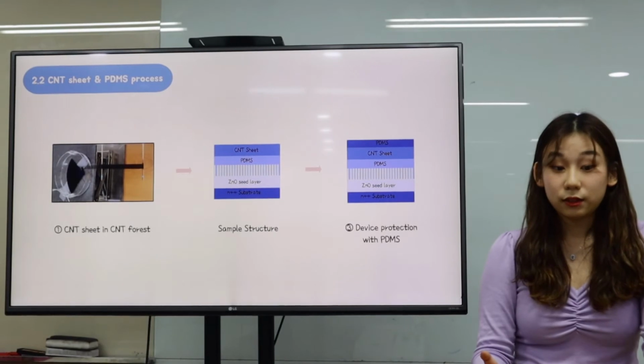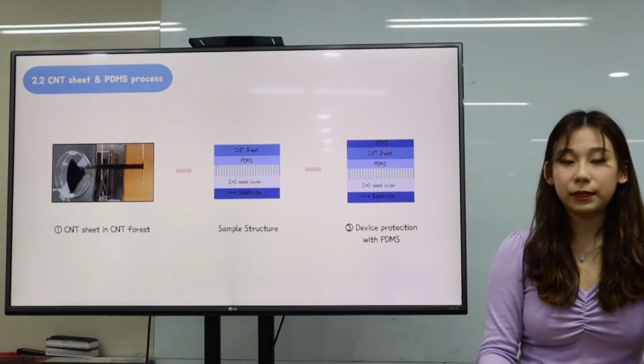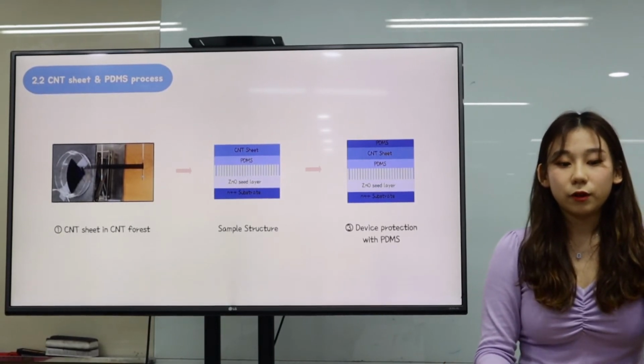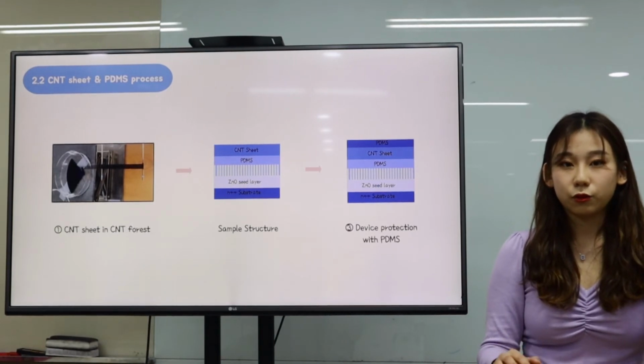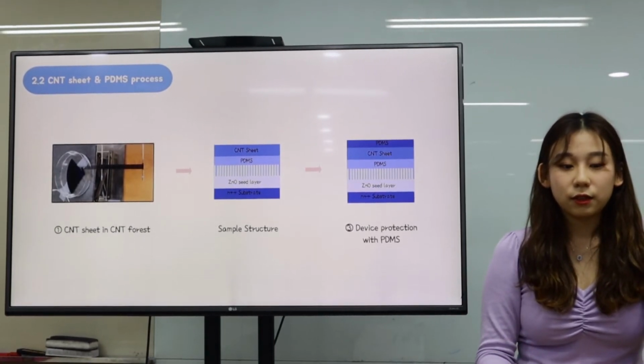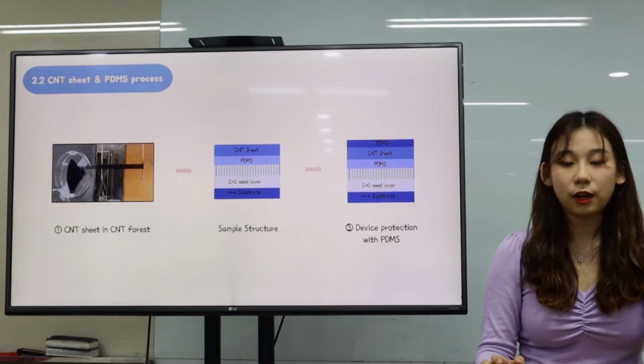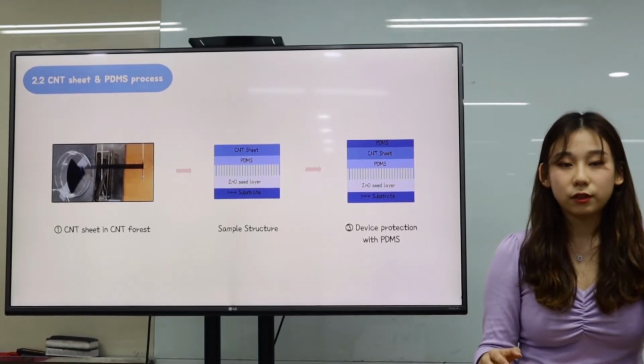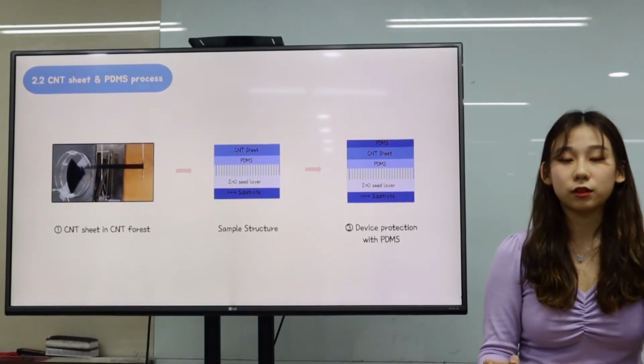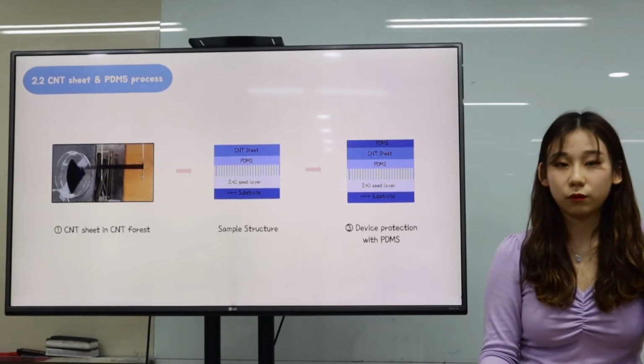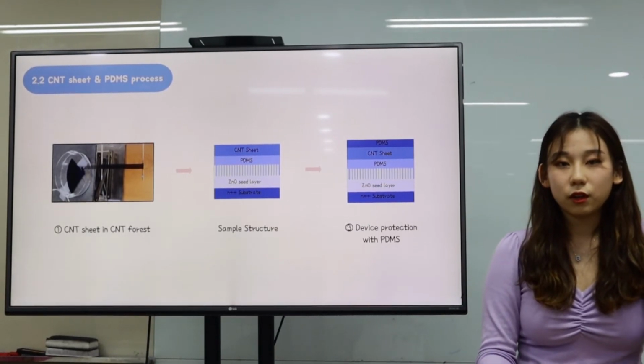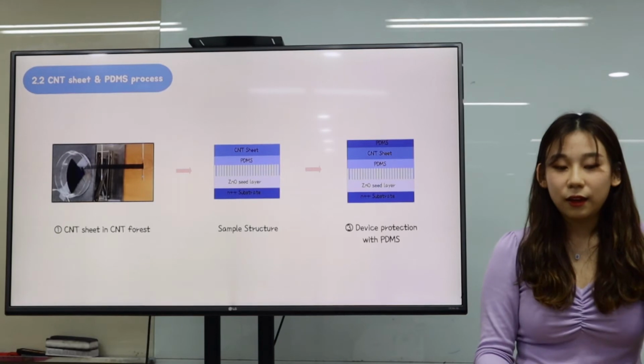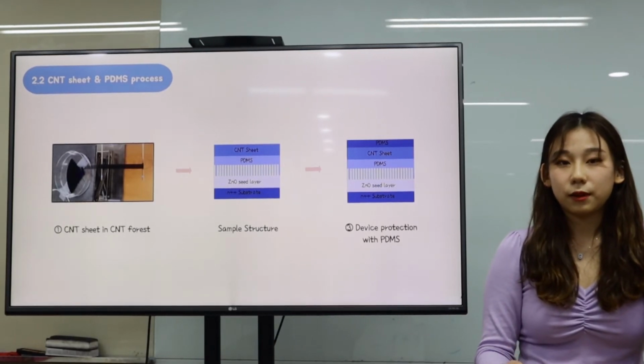Final is the CNT sheet and PDMS process. First, we use a CNT sheet as the upper electrode. This CNT sheet comes from a CNT forest and has very good conductivity because it is grown vertically. Second, put the CNT sheet on the pre-PDMS and then spread another PDMS layer to protect our device.